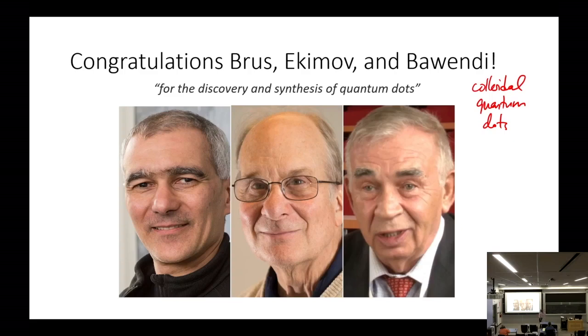And then the second part of the Nobel Prize is the synthesis of quantum dots. These two guys obviously made them, but they didn't make them well. Because the properties of these colloidal quantum dots and epitaxial quantum dots are related to the size, in order for these things to be useful, they need to be all exactly the same size. So if you're making them in solution, typically when you grow crystals in solution, you make lots of different sizes. So you have to exquisitely control nucleation, which is the moment the crystals are born, so they can all grow at the same rate, so that they can all become the same size.